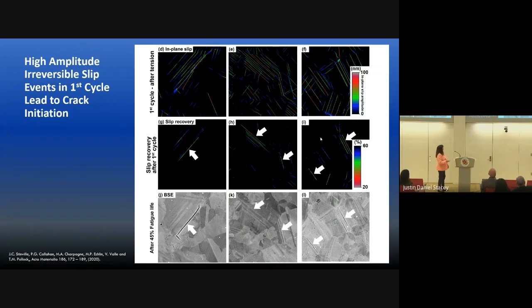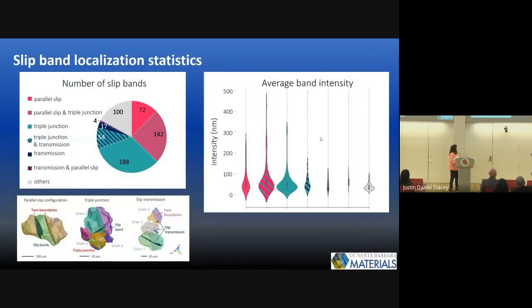So that's interesting. After one cycle, we might be able to detect where the damage is happening. And so with 3D data sets, we can not only know what's going on at the surface, but what's going on underneath. And so a couple of my postdocs spent a lot of time writing software to merge all of the data, correcting for all the distortions of the microscope and so forth, and superimposing the slip bands on the 3D microstructure.